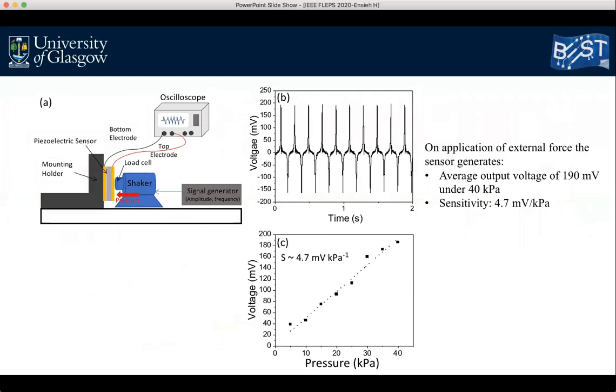And then we used a mechanical shaker that periodically generates a compressive load at a specific pressure, and the output voltage generated by the device under each applied pressure was measured using an oscilloscope here. And this figure shows the output voltage generated from the device under dynamic pressure of 40 kilopascal, and the voltage generation is quite stable and repeatable with fast response time. And it shows here that the generated voltage linearly increases with the applied compressive pressure, and the sensitivity of the device was about 4.7 millivolt per kilopascal, obtained from the slope of this curve.